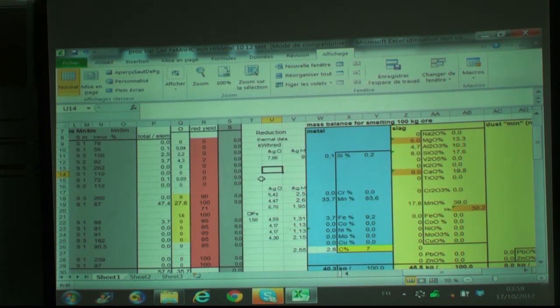It's not less gas. No. Because you see, when MnO2 plus CO gives MnO plus CO2, the number of molecules is the same. It's not less, it's not more.